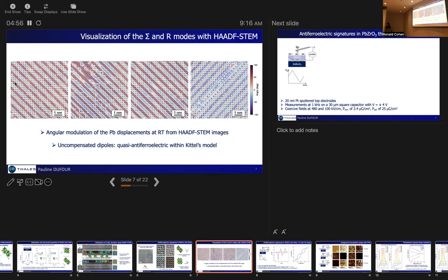And interestingly, if you look in more detail, you can see that all these lead displacements, antiparallel displacements, are uncompensated, which means that we have a quasi-antiferroelectric state according to Kittel's model. So we have seen that we could visualize the sigma and the R modes, which are characteristic of antiferroelectric PbZrO3 structure.